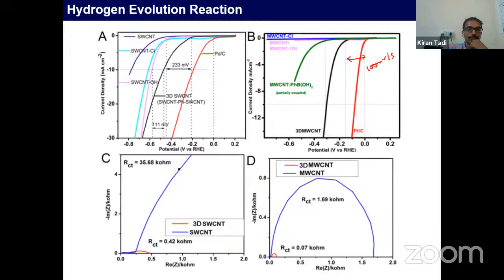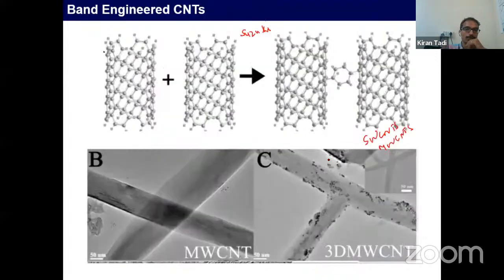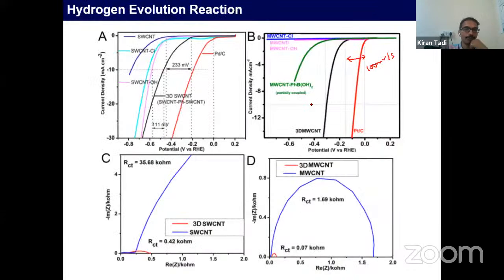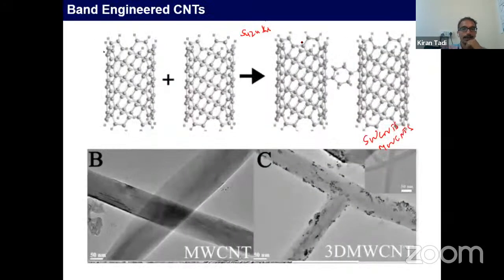Also, we didn't disturb the electronic properties of these CNTs, whether covalently connected single-walled nanotubes or covalently connected multi-walled nanotubes. You can see very low charge transfer resistance and high conductivity shown here. So in this way, I would like to give you one flavor of hydrogen evolution reaction using band gap engineered carbon nanotubes.